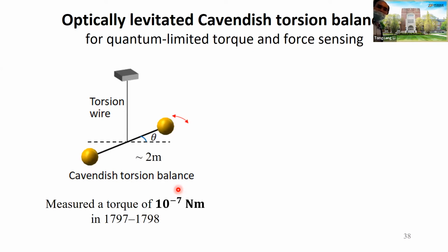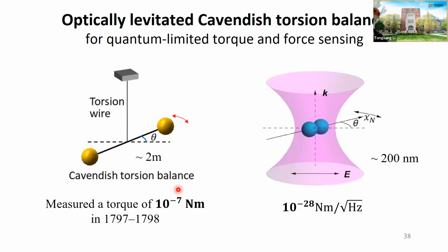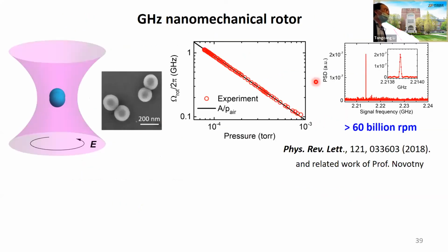In our experiment, we want to shrink down the Cavendish torsion balance from 2 meters to, let's say, 200 nanometers. Reduce the size by 7 orders. With that, we can improve the torque sensitivity by 20 orders, to 10 to the minus 28 newton meter per root hertz. To do that, we need to make these nano dumbbells, and we create them by chemical synthesis. So we can create silicon nano dumbbells, and if the laser is circularly polarized, the spin angular momentum of the photons will drive the nanoparticle to rotate.